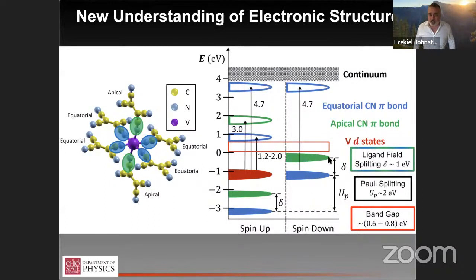And this splitting is huge for relevant energy scales. It's about an eV, and so this yields all kinds of interesting physics. So it's a fully spin polarized band gap. For one, it gives us some hint of where this strain dependent anisotropy comes from, because there's an inherent magnetic anisotropy in the crystal structure and various other things that are off to the races here. So we're very excited about this. This is hot off the presses. And I think this is not yet an answer about why this particular material.